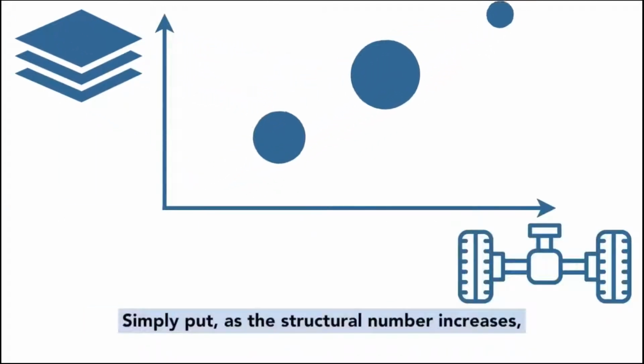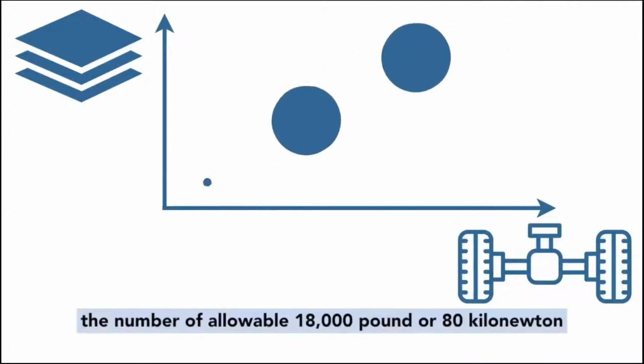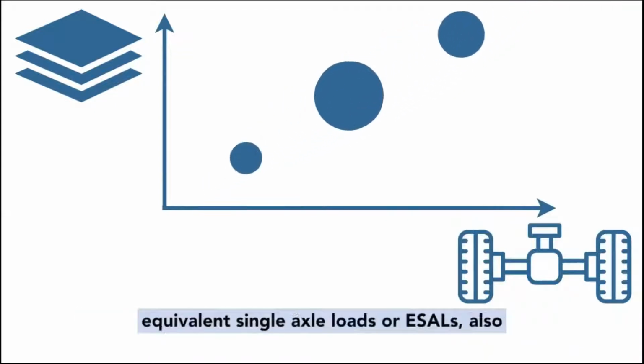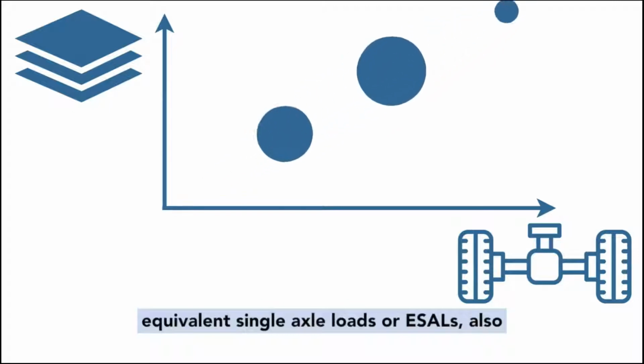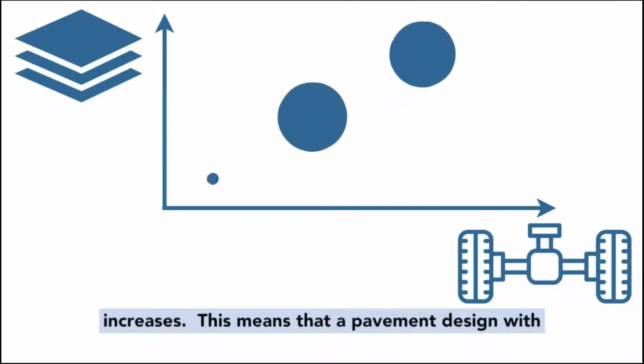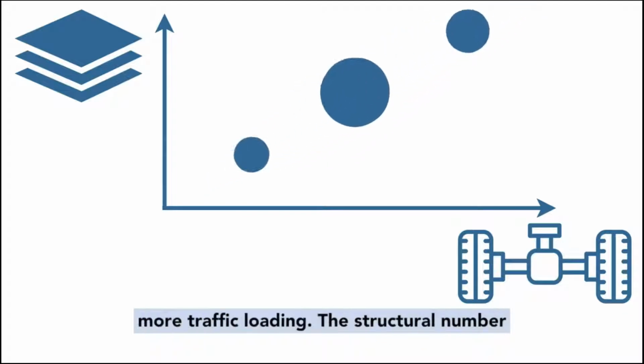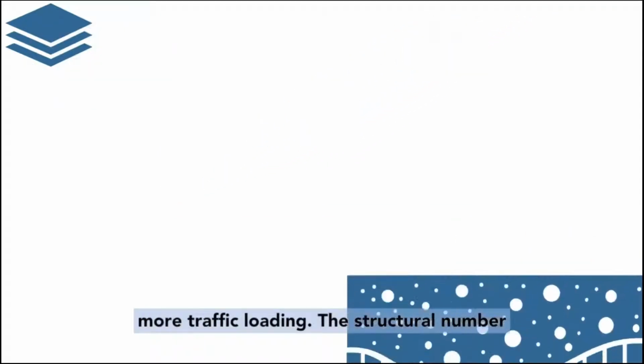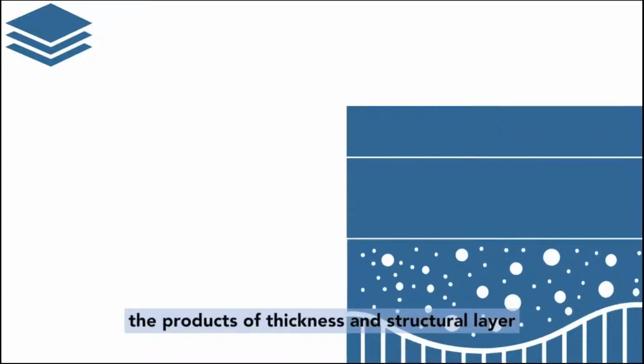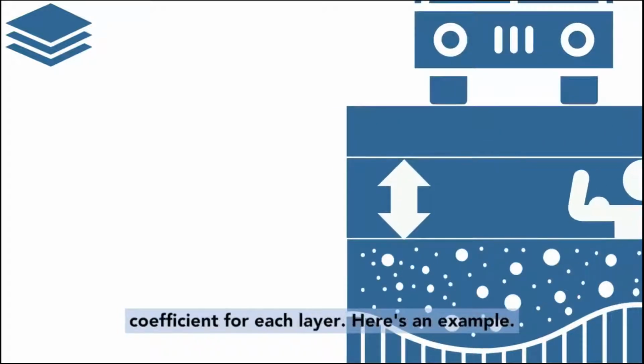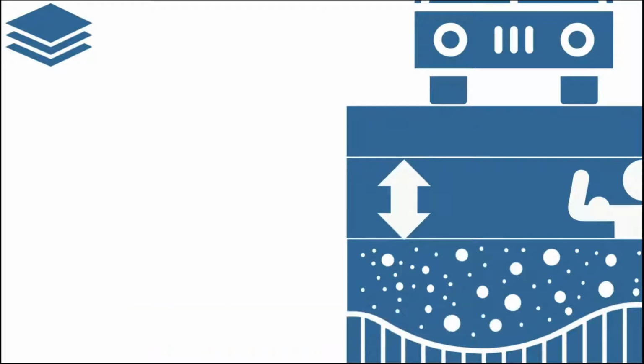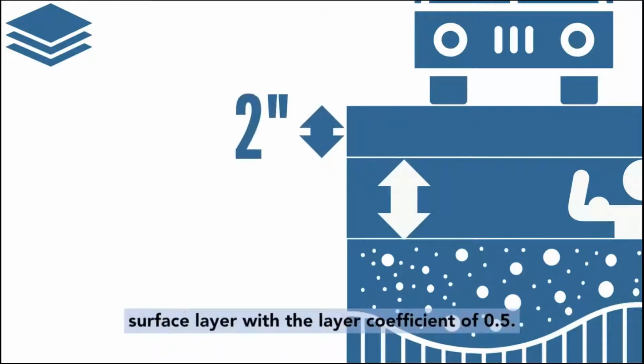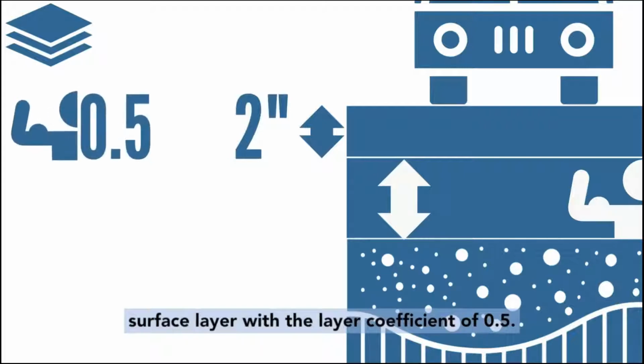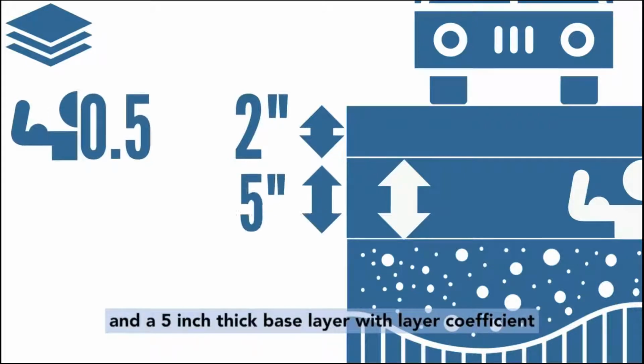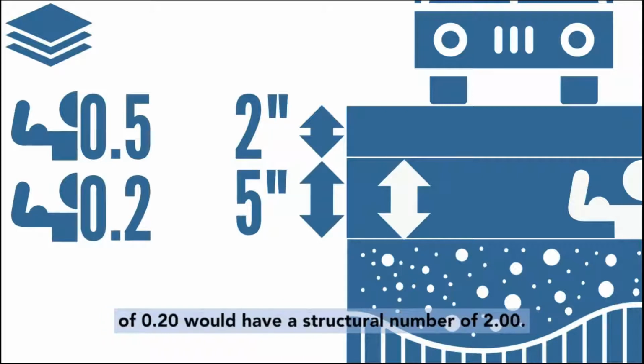Simply put, as the structural number increases, the number of allowable 18,000-pound or 80 kilonewton equivalent single axle loads, or ESALs, also increases. This means that a pavement design with a larger structural number can withstand more traffic loading. The structural number for a pavement design is calculated by summing the products of thickness and structural layer coefficient for each layer. Here's an example. A 2-layer pavement which has a 2-inch thick surface layer with a layer coefficient of 0.50 and a 5-inch thick base layer with a layer coefficient of 0.20 would have a structural number of 2.00.